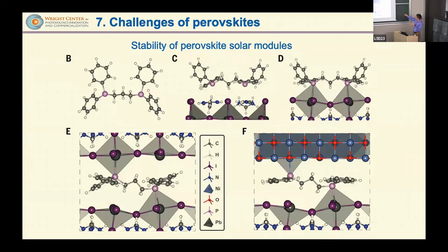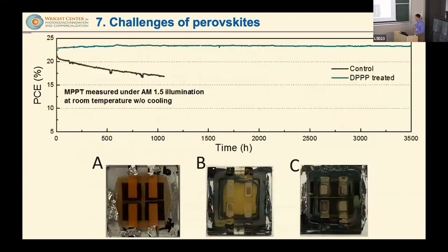So when we put those into our perovskite, let's say this is my perovskite, this is the lead, right? It has a very strong interaction with this phosphorus. And there's one side of a perovskite, and there's another side of perovskite, and it also has lead. This molecule can bond the two sides. So it makes a very good, strong bridge between them. We are making those surfaces more stable, not easy to move. Without this, it is essentially a defect. So we heal the defect, make the surface, grain boundaries, interface more stable, and they can also bind all those together. This will be a wonderful material, and then we, with collaborators, tried to make solar cells.